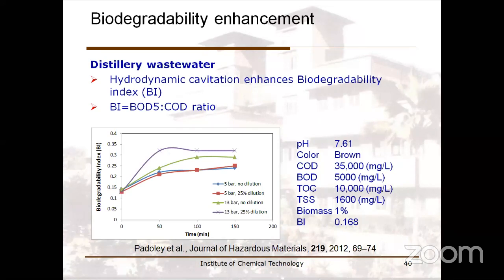So if we can say that hydrodynamic cavitation is going to enhance the biodegradability, what it's going to mean is it's going to enhance the efficacy of existing biological oxidation. Definitely that's going to be much more recommended and acceptable. So a typical range of biological index or biodegradability index is 0.3 to 0.5. So we started with a refractory effluent having a biodegradability index of 0.1. After treatment, you are reaching the magic figure of around 0.35. So within the definite range. So that is an advantage.